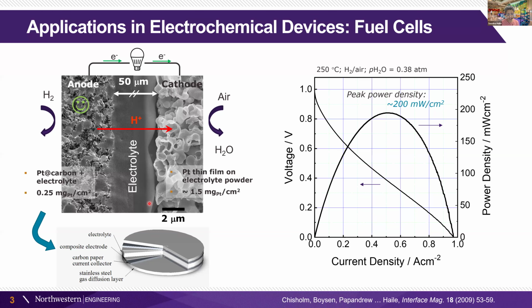Our anode is particularly effective. The platinum loading in the anode is moderate, 0.25 milligrams per centimeter squared. The platinum loading on the cathode side is not moderate, it's quite high. And our cathode is also the one that has longevity challenges. So that's the side in terms of the device improvements that we're working on. And I'll show you that it's connected to the electrolyte behavior. So that brings us to designing better electrolytes to allow the cathode functionality to improve.